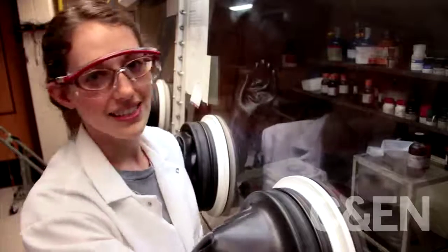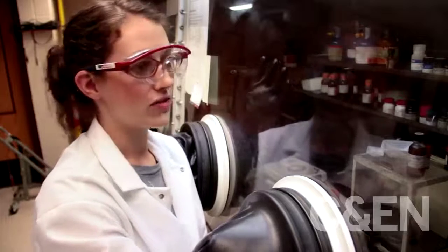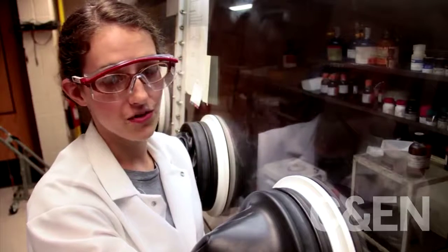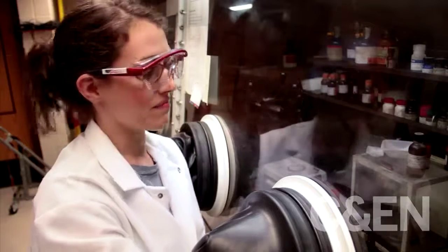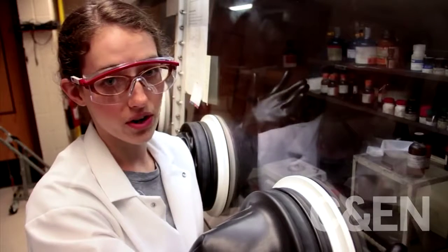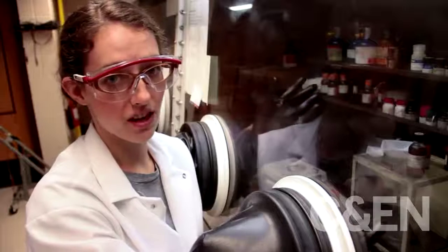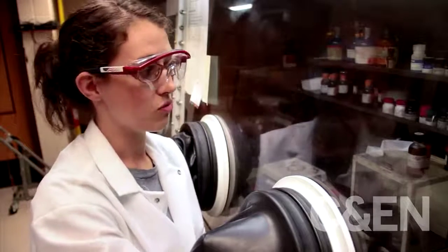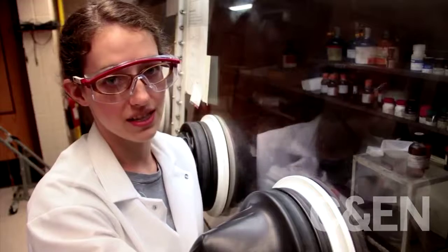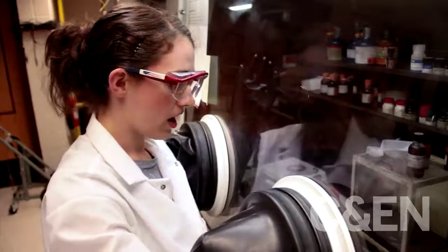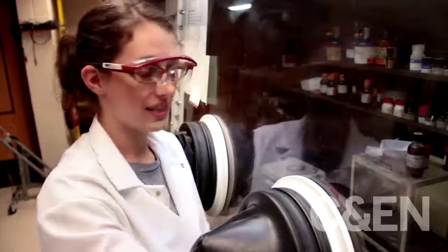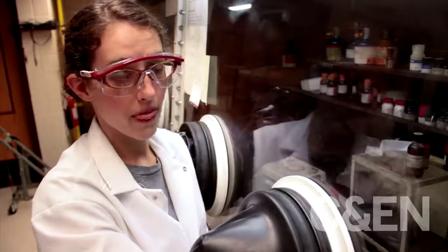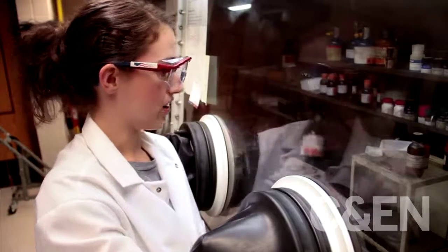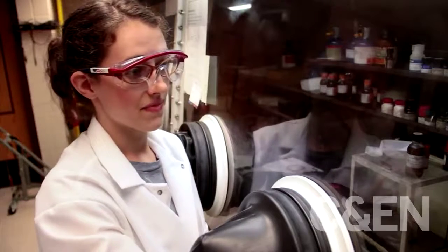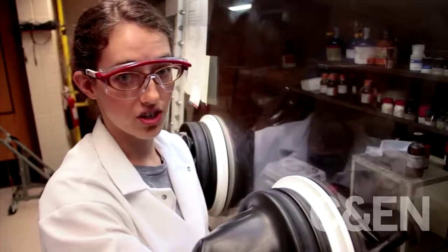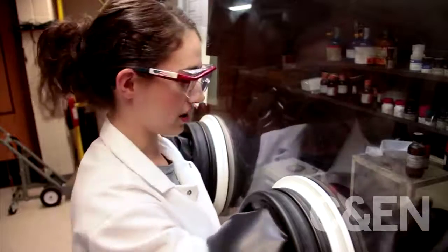So this is a glove box. It's filled with argon, and it serves two purposes. The first is to protect us from the chemicals. Some of them give off bad odors that could be harmful to the body, so we keep them in the glove box. And the second is to prevent the chemicals from degrading in the presence of air. So I'm getting two things in here. The first is selenium, which is in powder form, and then I'm going to dissolve that in tributylphosphine. And then I'm going to take that, split it between two syringes, and head back over to do the injection.